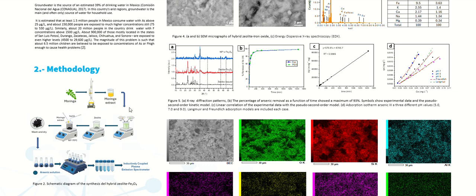The iron(III) and iron(II) were dissolved in distilled water. The zeolite was added and left to stand for 24 hours. The mixture was heated to 60 to 70 degrees Celsius, and 20 milliliters of moringa extract was added. The pH was adjusted to 13 with sodium hydroxide. The mixture reacted for 40 minutes. Finally, the material was washed 3 times with distilled water and dried.